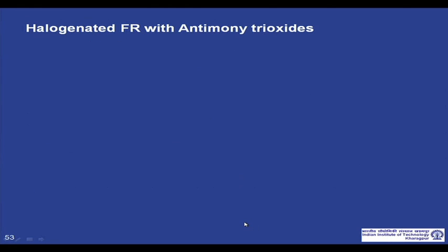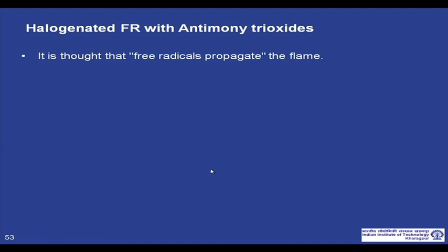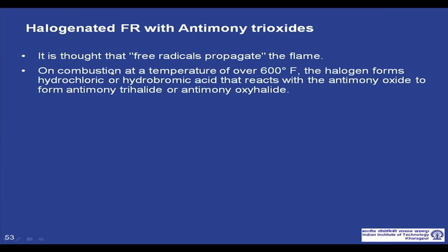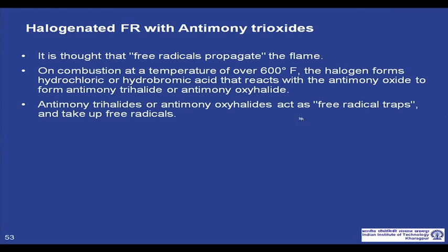A combination of halogenated FR and antimony trioxide is also used in some cases, and this is how it works. On combustion at a temperature of 600 degrees Fahrenheit, these halogens form hydrochloric or hydrobromic acids that react with the antimony oxides to form antimony halide or antimony oxyhalides, which basically trap those free radicals